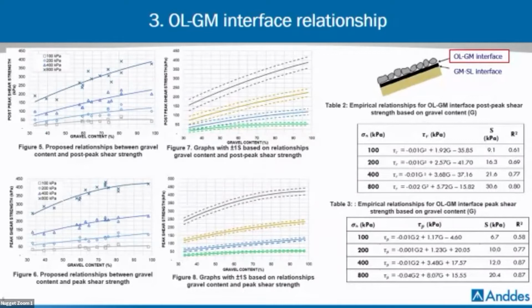The next slide shows the shear strength relationship for the overliner with smooth geomembrane interface. A relationship for each normal stress was defined based on the influence of the gravel content. Most of the data were obtained from tests of interfaces with LLDPE geomembranes. The thickness of the geomembrane has not been considered. Also, the overliner corresponds to subangular and subrounded gravels. The maximum particle size of overliner was 3 inches, and the maximum normal stress was 800 kilopascals for the tests.